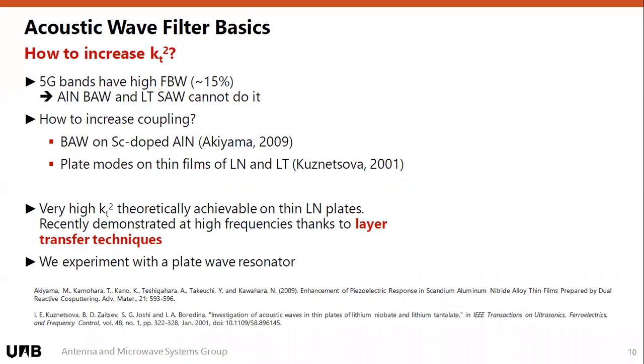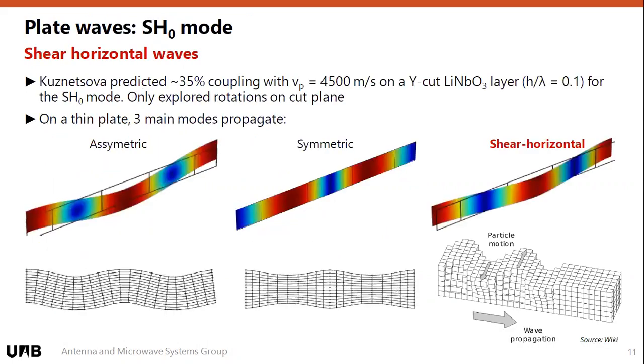And there have been a lot of demonstrations using these modes, especially, for example, a company called Resonant that demonstrated what they call the XBAR. It was a thin layer of lithium niobate providing a coupling above 30%. That was a kind of revolution. They are running into other problems, but they started demonstrating these structures. What we're going to do is build resonators using this same approach, the plate wave resonator with a thin lithium niobate film.